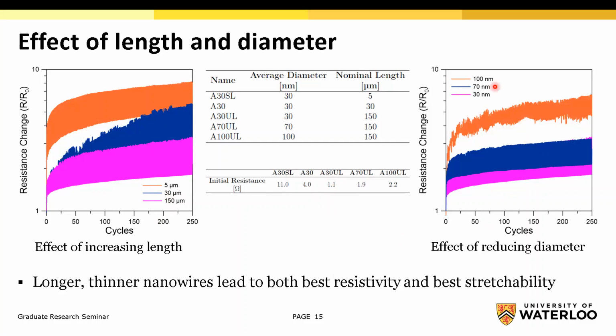And if we take a look at the different diameters in the same plot, you can see 100 nanometer, 70 nanometer, and 30 nanometer, and stretchability increases with reducing the diameter as well. And also from the different diameters, the 30 nanometer one has the lowest initial resistance, which means that stretchability and conductivity increase with reducing the diameter and increasing the length of the nanowire inks.